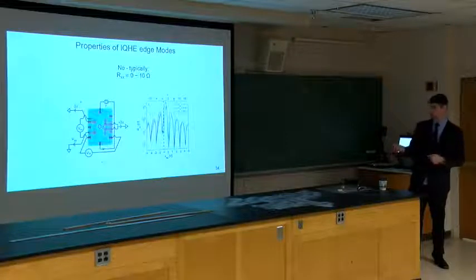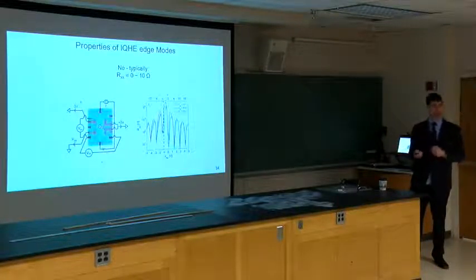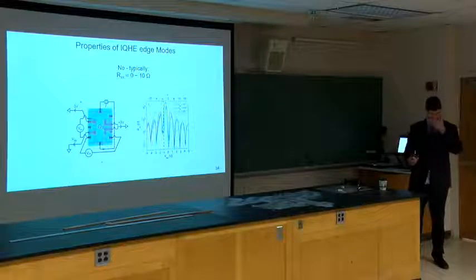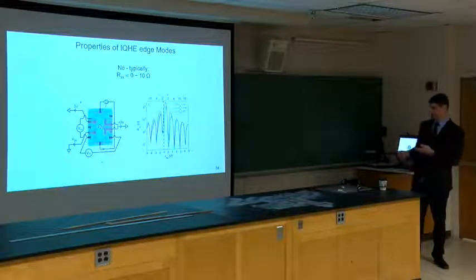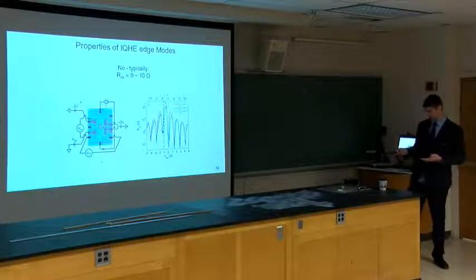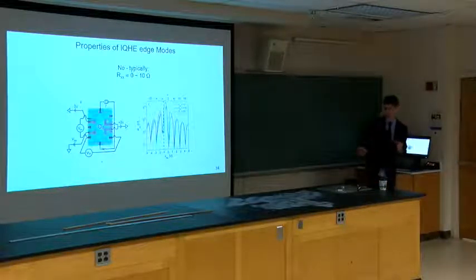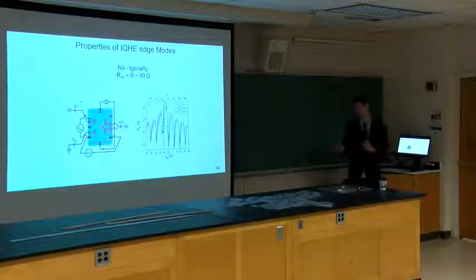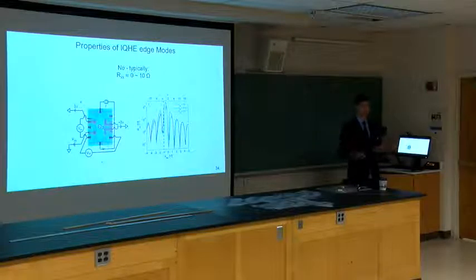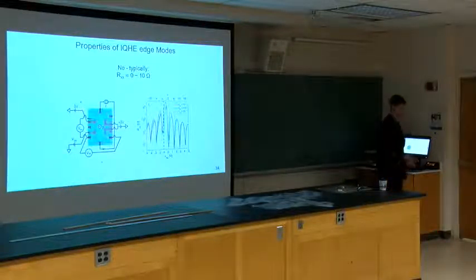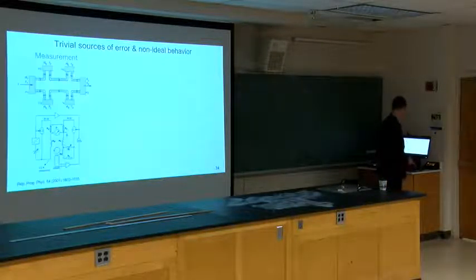It should be 0, but if you do it in a logarithmic plot, it never goes to 0. Even if you change the current, change gate voltages, anything, it's never exactly 0. So in truth, it's usually between, I'd say, 0 and 10 ohms. It's something like milliohms to 10 ohms in good devices. In bad devices, you can get more.